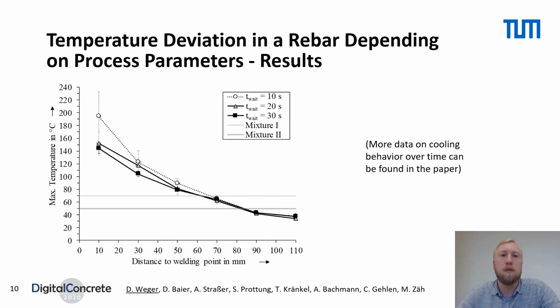Now let's have a look at the results. The diagram on the left shows the maximum temperature at every measurement point. Furthermore, the light gray line shows the acceptable temperature for mixture 1 and the dark gray line for mixture 2. In the paper you can find a further diagram that exhibits the mean temperature development depending on time after welding. The diagram in this presentation shows that the temperature decreased very fast from approximately 1500 degrees Celsius at the welding point to the first measurement point 10 millimeters away from the welding point.